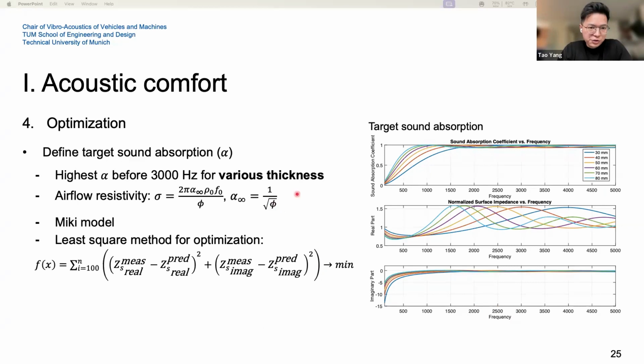That's another target. We find the highest sound absorption before 3000 Hertz for various thicknesses, for example, from 30 millimeter and 40 millimeter to 80 millimeter. Same as the previous slide, we calculated the airflow resistivity and got the tortuosity, and also used the Miki model to plot the target sound absorption and also the normalized surface impedance.